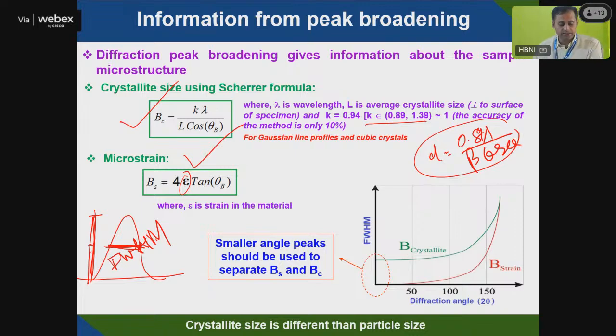This is strain. So you can calculate easily your crystallite size and your strain from this peak broadening. When you go for peak broadening, you can see here, this is your beta crystallite size varying like this, and this is your beta strain. So always you take a lower angle peak so that beta crystallite and beta strain lie separately. If you take a higher angle peak, they are closer to each other. So smaller angle peaks should be used to separate beta strain and beta crystallite.